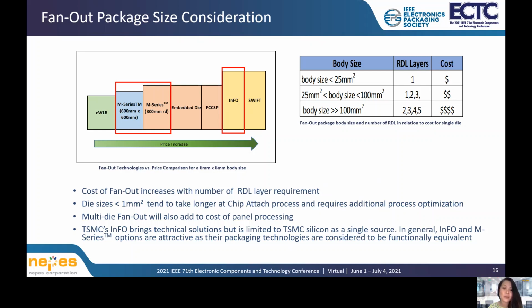model. What we found is that the sweet spot in panel level packaging process for non-package on package is between 4 mm squared to 64 mm squared body size. Body sizes outside of this range will require additional process optimization.